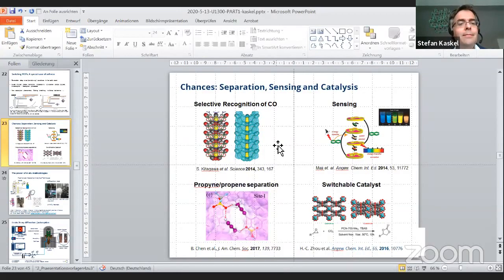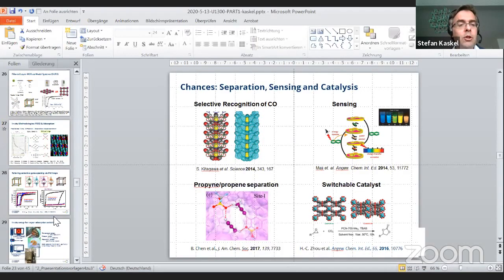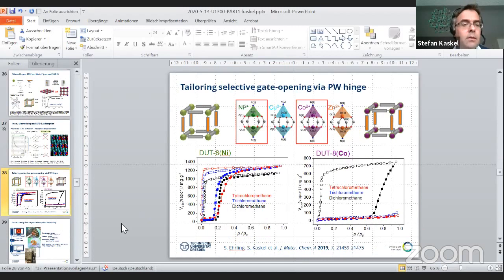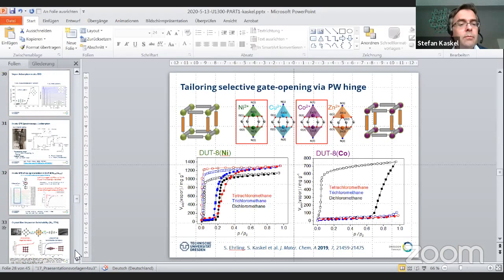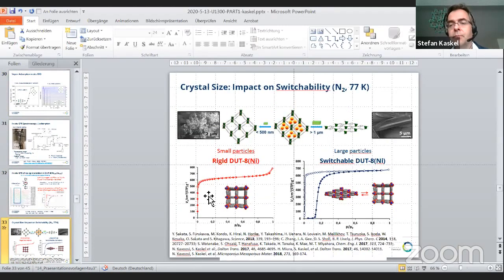Okay, thank you. The second question is from Anaga Bhattacharya. What is the heat of adsorption for these materials, and how do they compare to non-switchable adsorbents? I come to this point a little bit in my second presentation, but the heats of adsorption are not in particular special. Here we have a model material, which we can synthesize as a rigid and as a switchable material. And this allows us to measure the heats of adsorption for the rigid variant with the same chemistry, basically, and compare it to the switchable adsorbent.